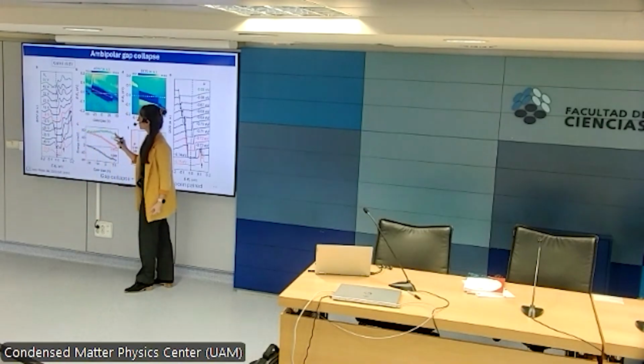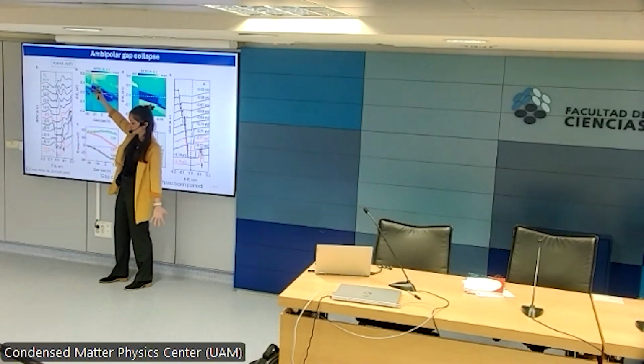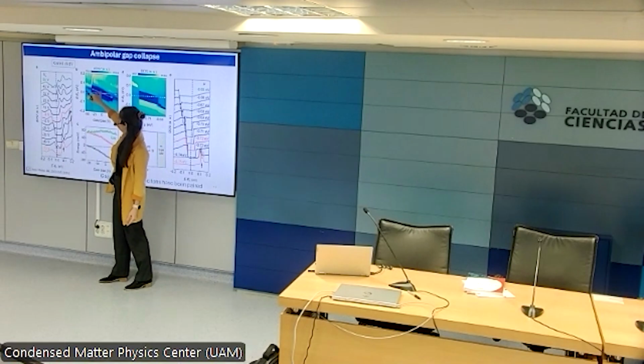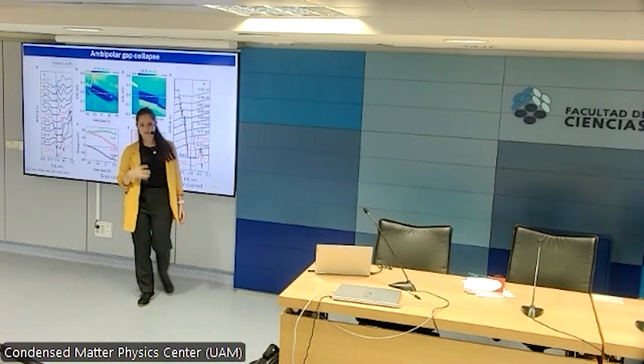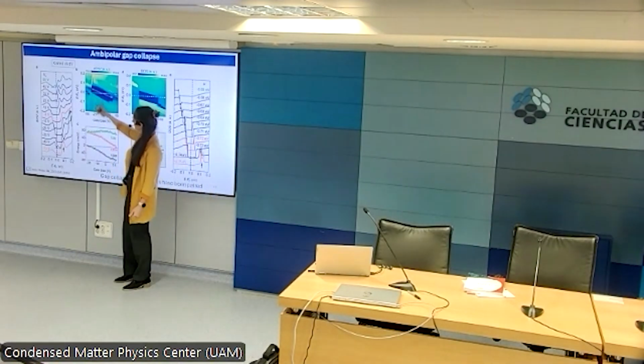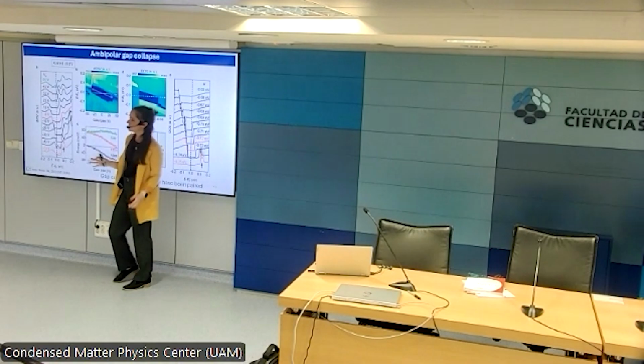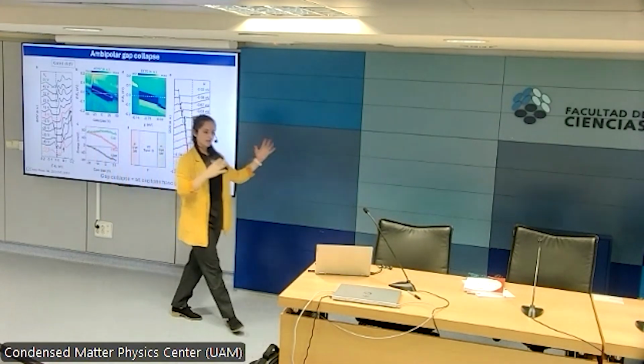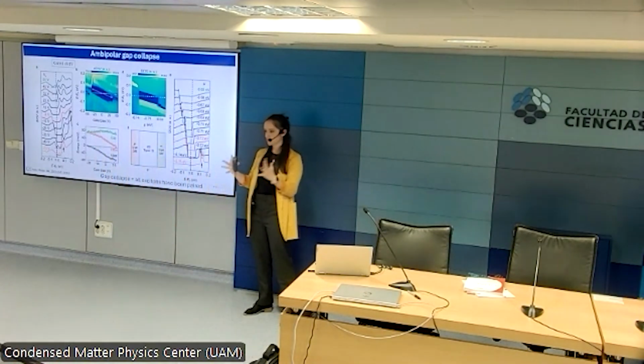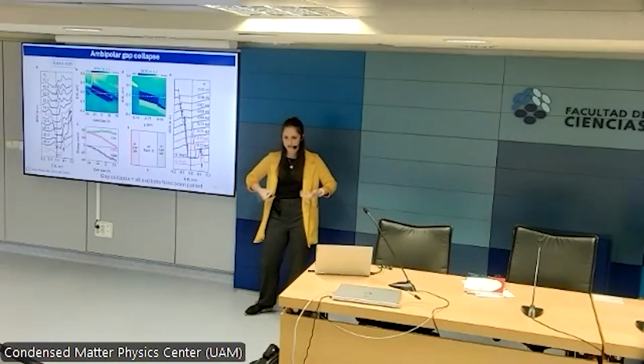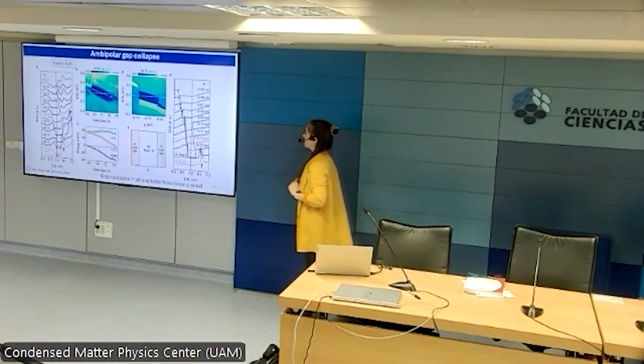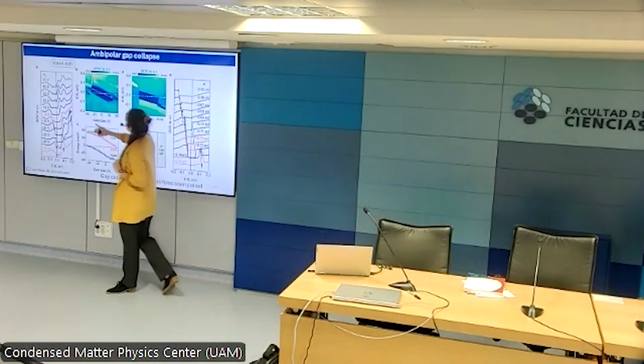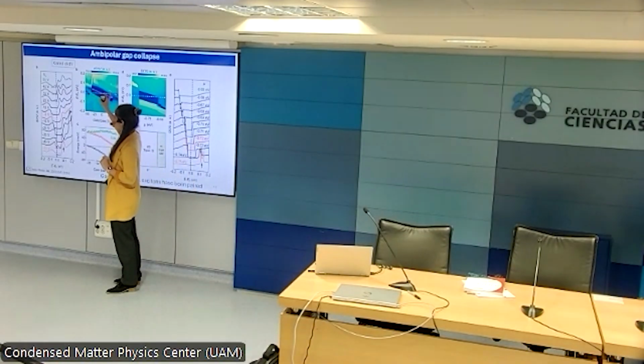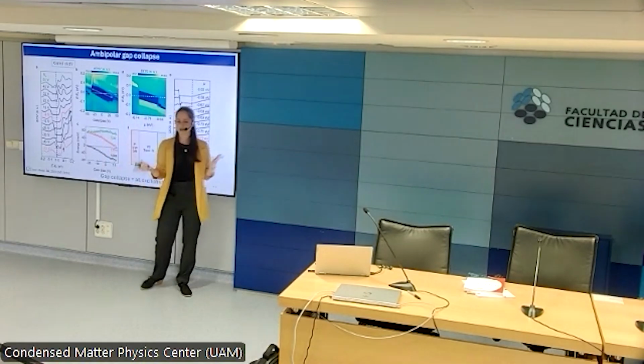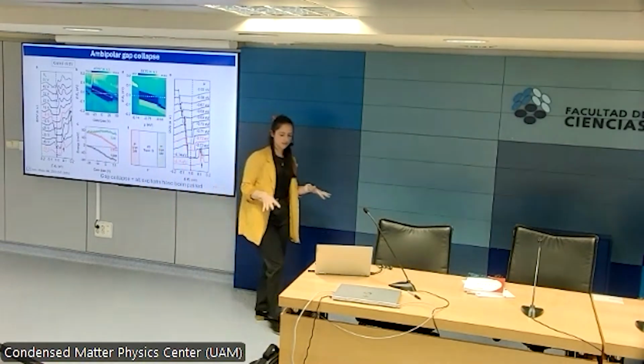Let's move to this plot, which is much prettier. It's the same plot, just in a heat map. So blue indicates where the band gap is, and then the green, yellowish part is where the states are. So you can see that at 0 bias, you have the band gap, states and states, and then they start gating the system. Normally, when you gate the system and you apply a bias, you have a rigid shift of the band structure, because what you're doing there is just moving the Fermi level up and down. What they observe instead is that when the band gap touches the Fermi level on one end or the other, so positive or negative bias, the band gap collapses. So there's no band gap in the system anymore.